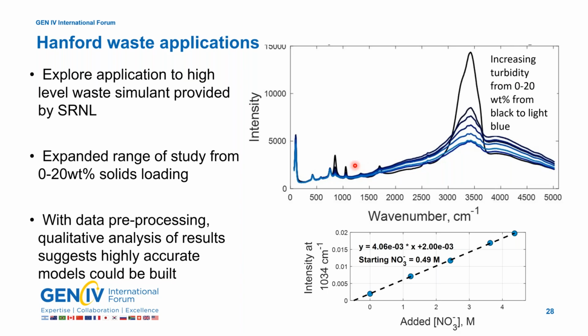The band I want to focus on is this one right here at 1050 wave numbers. That's the nitrate band. Through pre-processing of this data, we can then see that band at 1034 wave numbers, that's the nitrate band. It still maintains very nice linearity, even at 20 weight percent solids with added nitrate.